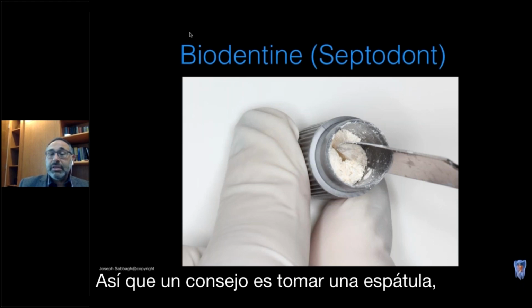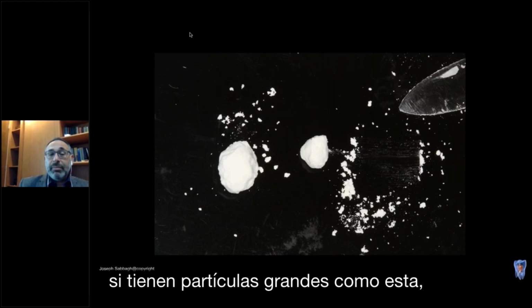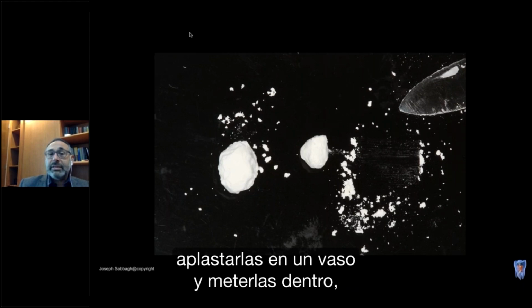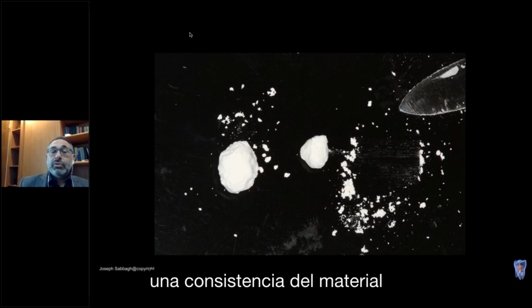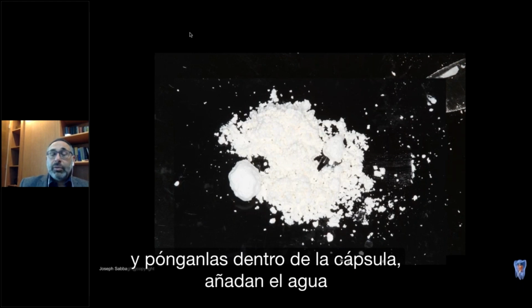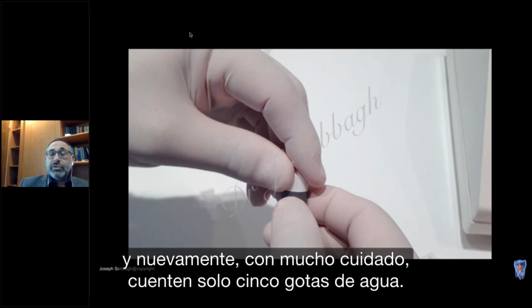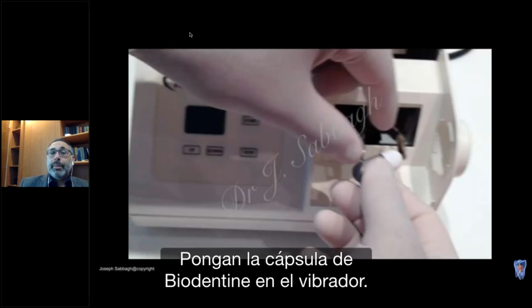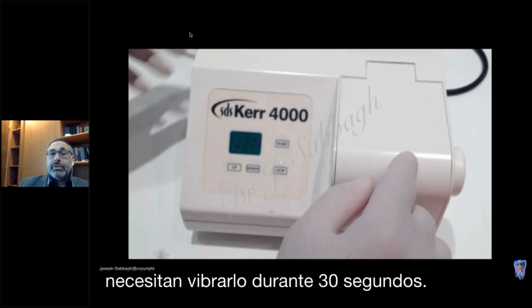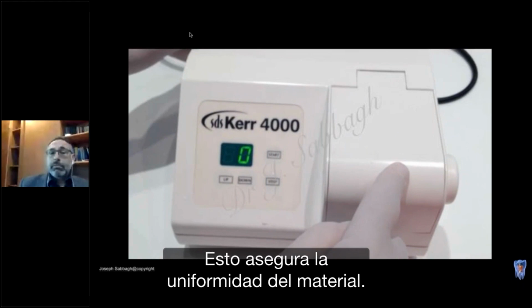So one piece of advice is to take a spatula, you put it inside, and you try to remove them. If you have big particles like this one, you crush them on a glass slide and you put them inside. And this will ensure a more uniform consistency of the material to have it really like you want. So you crush, as I told you, the big particles, and you put them inside the capsule. You put the water, and again, be very careful, just count 5 drops of water, and you put the capsule of Biodentine in the vibrator. And as you can see, you need to vibrate it during 30 seconds, and this will ensure the uniformity of the material.